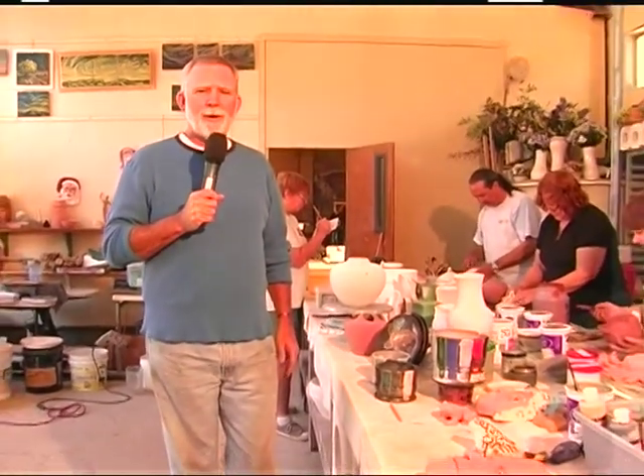Hi, I'm Tim Hanrahan, and today we're doing a Raku workshop here at Quyle Kilns in Murphys, California. Raku is an ancient Japanese form of pottery whereby you take fired pieces, bisque fired pieces, put them into a gas kiln, heat them up to 1800 degrees when they're glowing orange hot, pull them from the kiln, and place them into a reducing chamber, which is normally a metal garbage pail filled with combustibles, which would be shredded newspaper, pine needles, sawdust, anything that will create fire.